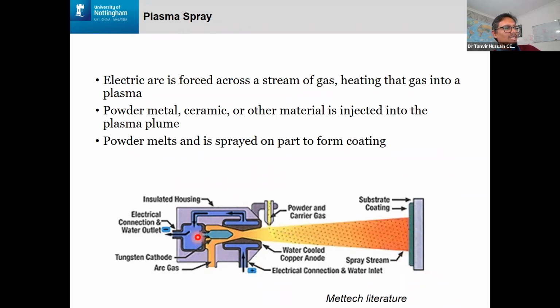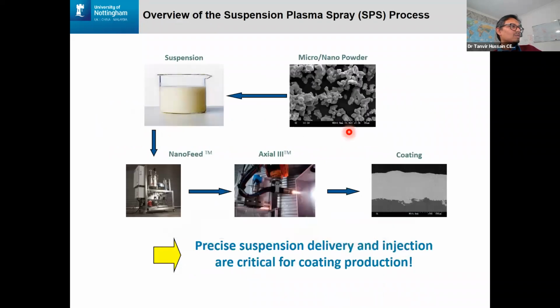What the suspension plasma does, and axial, instead of doing things radially, it injects things axially, which comes with its own processing challenges. And instead of using powder, a typical plasma spray powder is around 5 to, let's say, 100 micron, whereas the suspension system operates with particles of 10 nanometer to 5 micron. So it's operating in a very sub-micron to nanoparticle range.